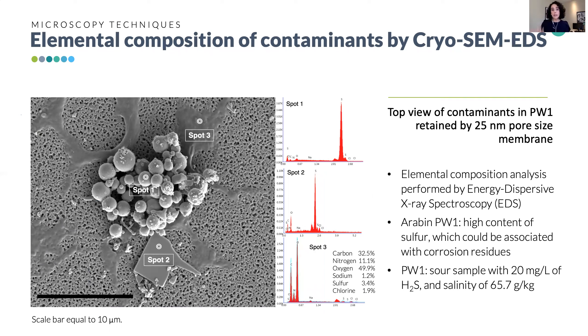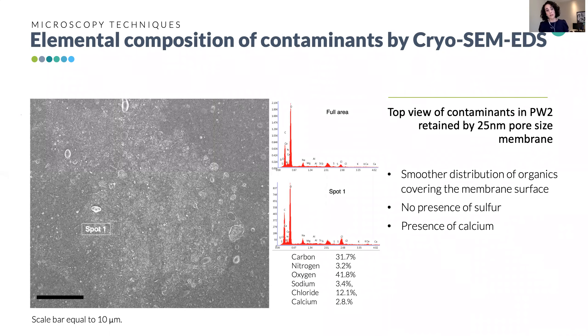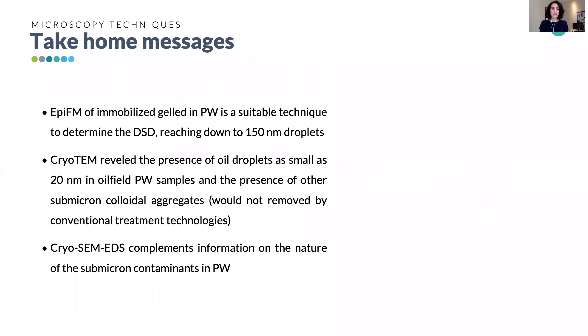The top view of the contaminated filter was taken by cryo-SEM — in this case the objective was to analyze the elemental composition of the contaminants using EDS. In PW1 we found brown, flat solids with high sulfur content, which could be associated with corrosion residues, as PW1 was sour and saline. In the Bahraini PW2, we found a smoother distribution of organic matter covering the membrane surface with no evidence of sulfur but some calcium. As a conclusion from electron microscopy, the gel immobilization epifluorescence technique was suitable down to 150 nanometers, and cryo-TEM revealed the presence of not only submicron droplets but also submicron colloidal particles in higher density.